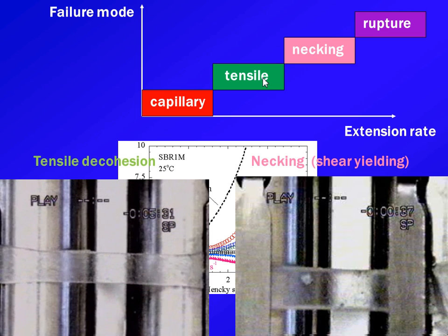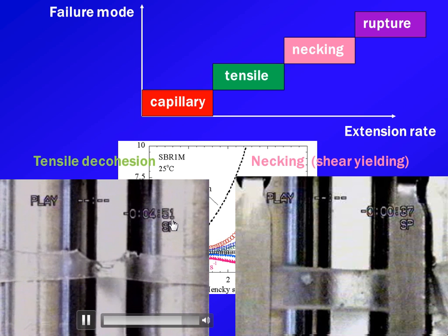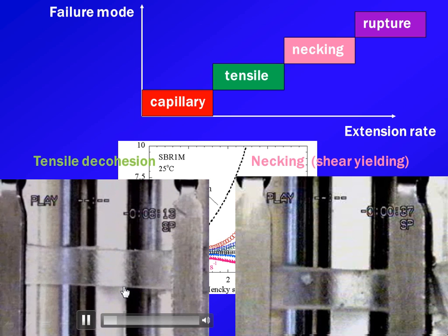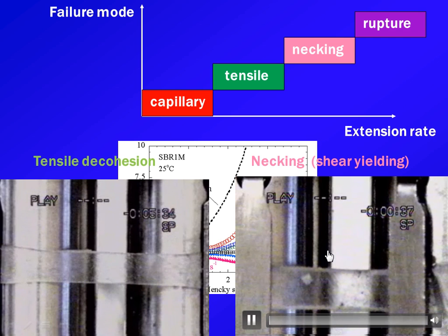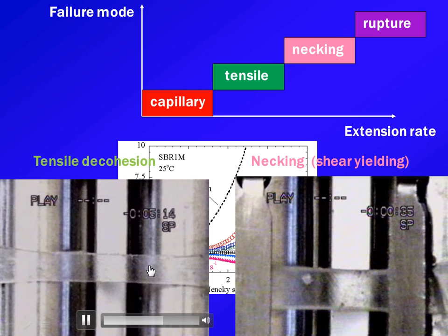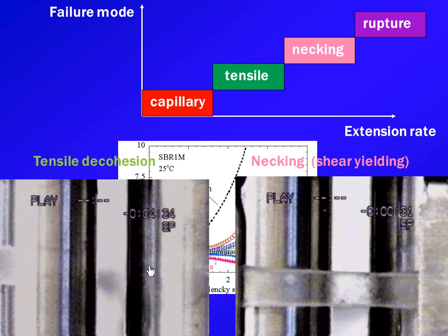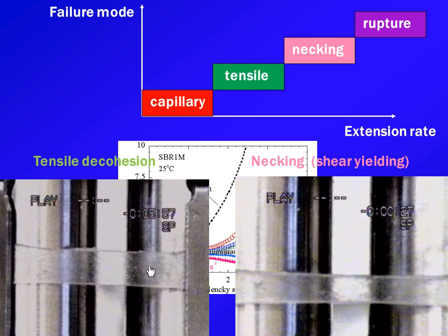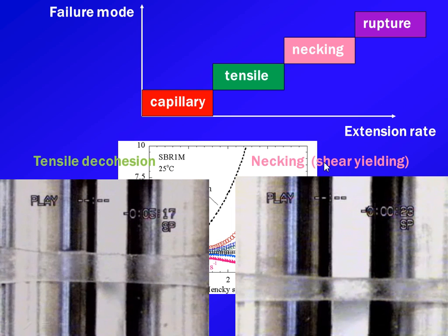There is one that we call tensile failure. You watch, it happens at low rate. This movie is sped up. Look at that. It breaks very sharply, quote-unquote, rupture-like. And then when you go to a higher rate, they stop behaving like this. The contrast between them is quite drastic. It doesn't do that vertical rupture-like behavior. And instead, you may call it necking.